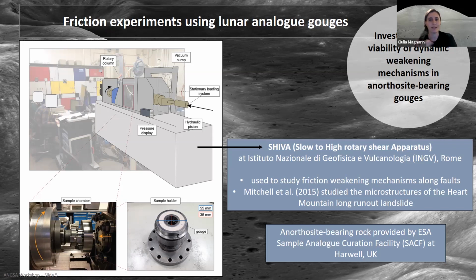So anorthosite-bearing material would represent an analog for the South Massif forming material, although we are learning that the lithological composition of the South Massif is far from being so simple. Anyway, we requested anorthosite-bearing rock from the ESA sample analog curation facility. And we then ran some friction experiments with SHIVA, the slow to high velocity rotary shear apparatus at the National Institute of Geophysics and Volcanology in Rome. So we ground our rock to obtain a gouge and put it in a sample holder, which is then put in the sample chamber. So from one side we have a stationary loading system. From the other side we have a rotary column, so that we can generate displacement for several meters. Next slide, please.